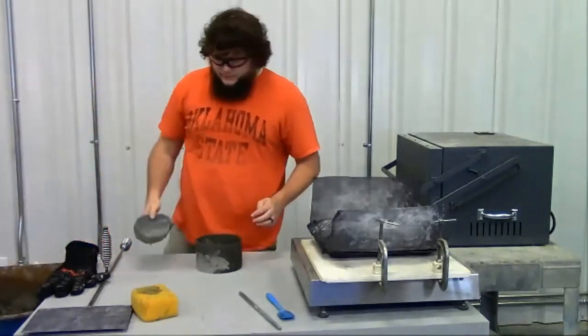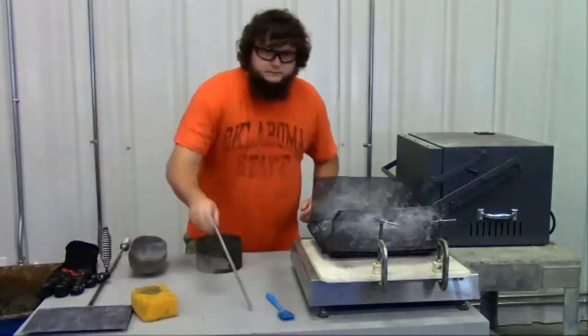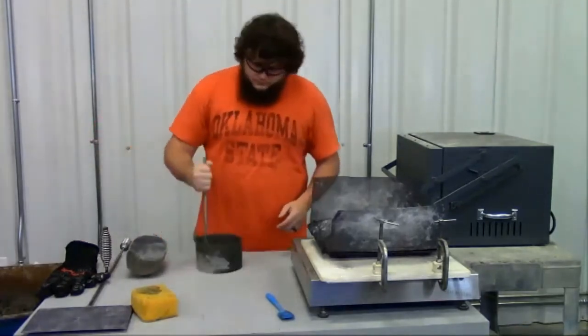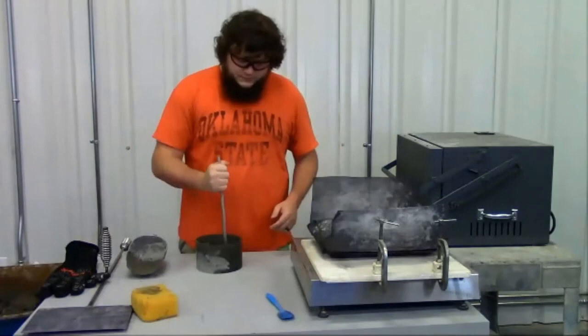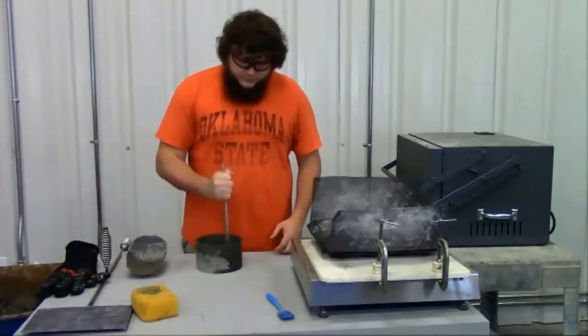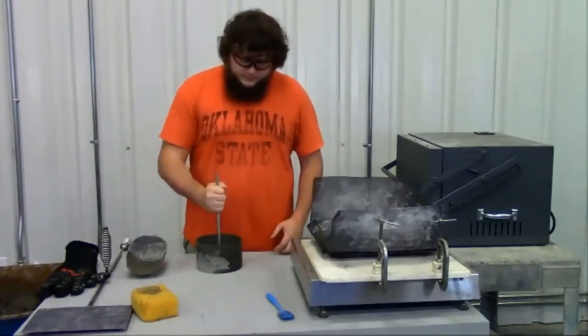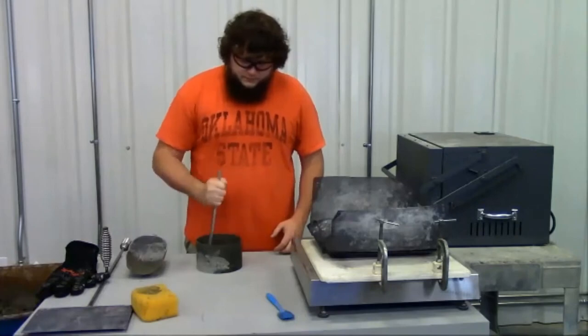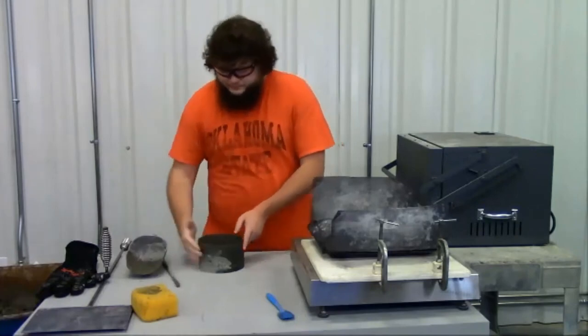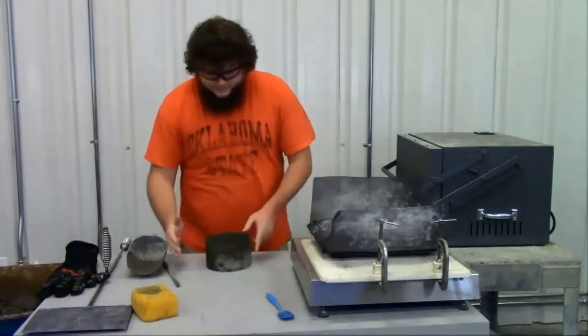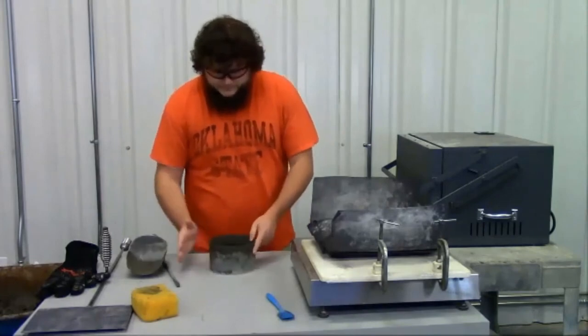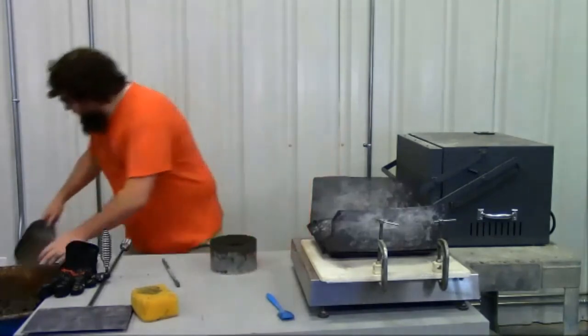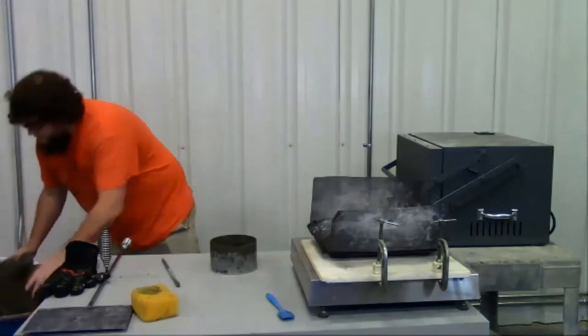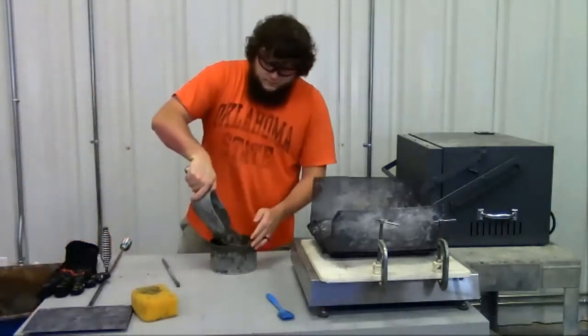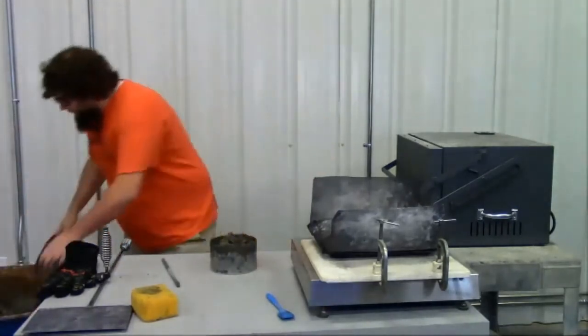The sample size is a 4x8 cylinder of concrete. We use a cut down 6x12 cylinder because it's easier to fill and empty. To run the test, preheat the kiln with the set point of 1500 degrees. This generally takes around 20 minutes before you actually want to perform the test.